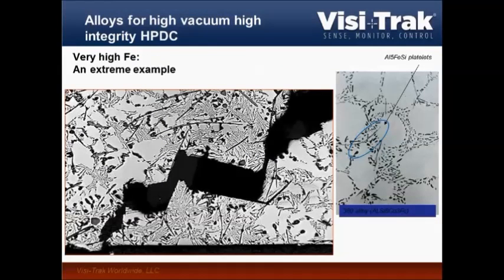So here's a picture of what the iron actually does. Both of them are 380 die castings, and in a 2D picture you will see it as needle-like structures. In 3D it's actually platelets, and they can be so nasty and go through your part that they actually cause it to crack. But at least they will block the feeding path and ruin your ductility.